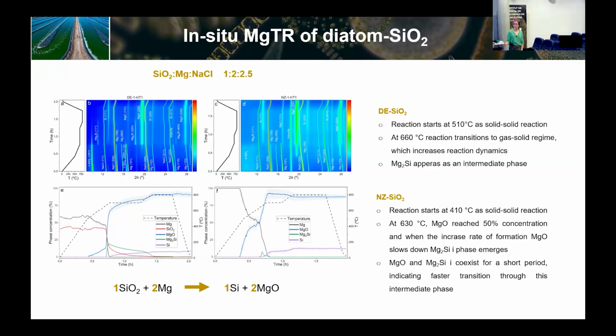One of the key findings is that at the beginning the reaction proceeds through a solid-solid regime. And this solid-solid regime, before magnesium actually evaporates, happens more when the material is amorphous and thin. So this means that magnesiothermic reduction could maybe be a solid-solid process if the material is good enough. But if the material is too thick or too crystalline, then you need magnesium to evaporate just to be able to go inside the particles and react with it.